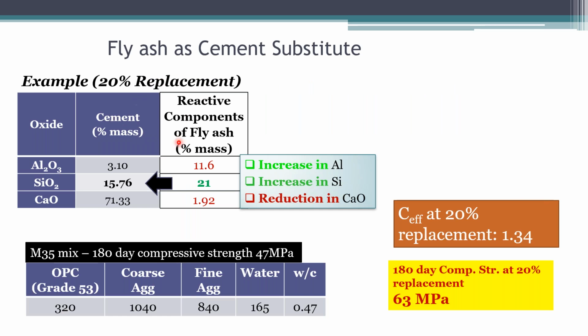And just to illustrate this, so we basically looked at a 20% replacement, which is typically what is done with fly ash. So here's the cement composition that we have: the alumina, the silica, and the calcium. And you can see the cement has a very high calcium content. 71% of cement is basically calcium oxide. These are the reactive components of fly ash, and you can see that it is completely calcium depleted. It's only about 2% calcium oxide, but it has a high reactive silica content. So when I do replace this, I can increase the silica content in my binary blend by bringing in fly ash. Now, at 20% replacement, we found that it gives us an efficiency factor of 1.34.